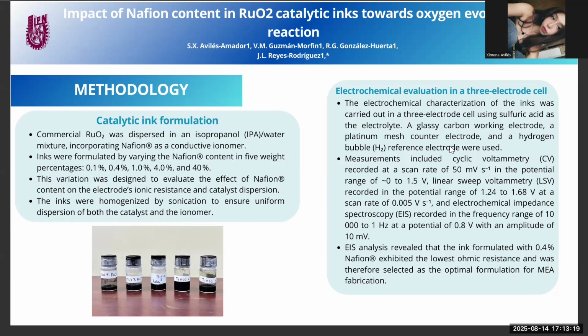We performed cyclic voltammetry from 0 to 1.5 volts at 50 millivolts per second, linear sweep voltammetry from 1.24 to 1.68 volts at 5 millivolts per second, and finally electrochemical impedance spectroscopy from 10 kHz to 1 Hz at 0.8 volts.